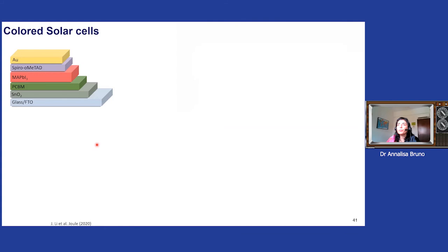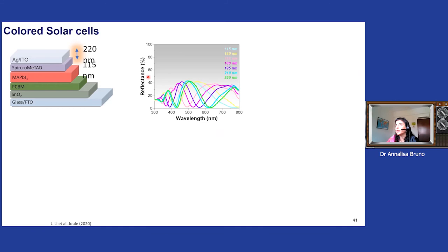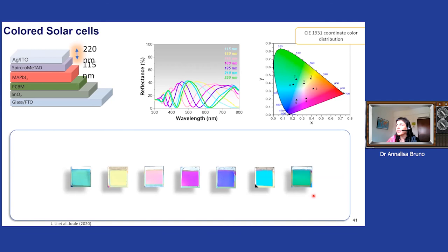What we have done, we have changed our top electrode with a different top electrode that is semi-transparent, because our previous one was based on gold, so it was not transparent. And we have tuned the thickness of this interlayer, and we can see that changing from 115 to 220 nanometers, we change basically the reflectance of these cells, and we can develop cells of very bright different colors. So this is a distribution of these cells,